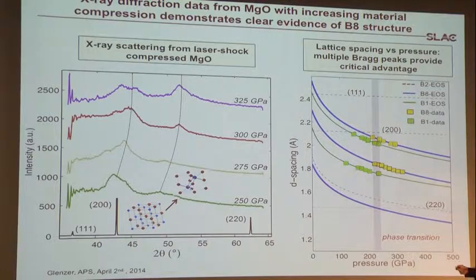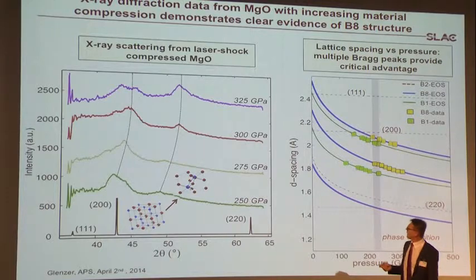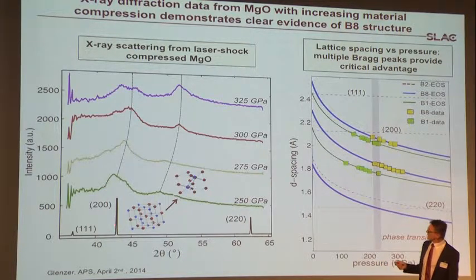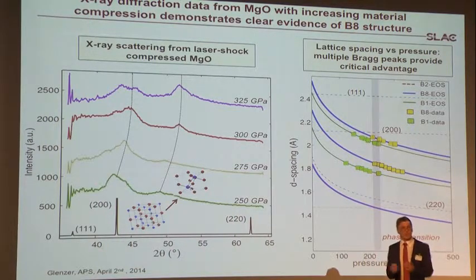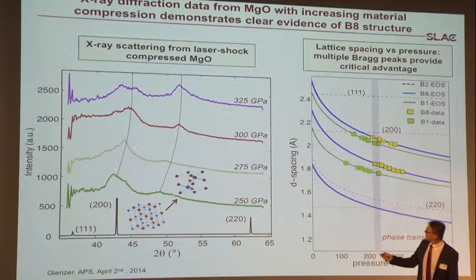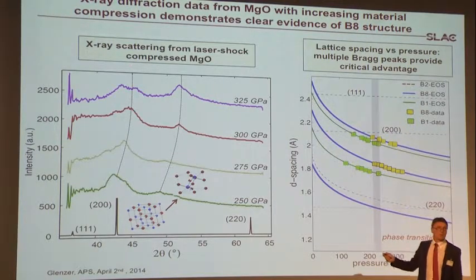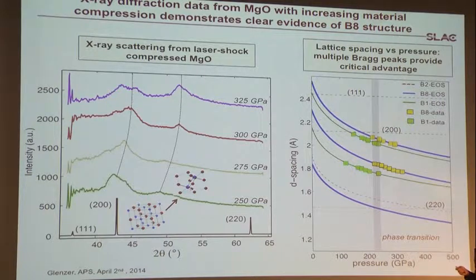So let's look at magnesium oxide. We've done X-ray diffraction. So this is magnesium oxide. This is the B1 phase. Now we shock compress the material. You can see, first of all, the 220 peak is actually broadening out. But then you see a double peak and a new peak coming up. And this peak is actually growing in amplitude. And this peak is actually shifting further out. So what that means is, as you're compressing the material, the Bragg peaks are shifting in theta, or in angle. That means you can follow an equation of state curve, the d-spacing versus pressure.